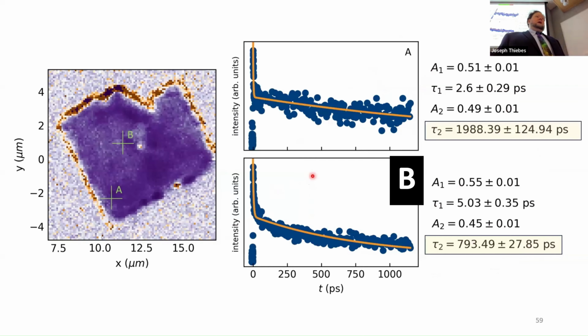And so we just started looking at what we would see. This is a pump probe image of a crystal of this bismuth oxybromide. And then I have two sites where I took kinetics data. So we're just looking at how the excited state decays over time. And I just highlighted the figure of merit to look at here, which is that, oh, that should say B, I'm sorry. So in this case, this is A, this top one, and that's sort of the edge/corner. And that has a lifetime of about 2 nanoseconds. The one in the interior is less than half of that lifetime.